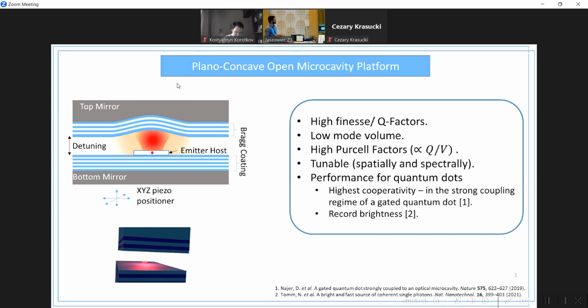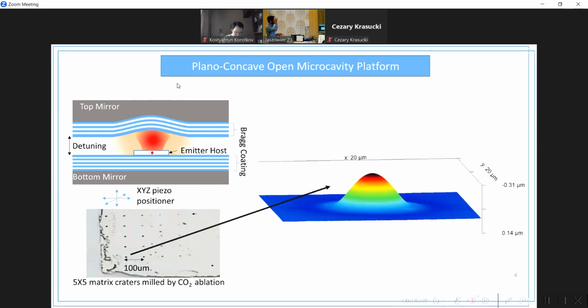Moving on, let's take a look at the sample that we have. This is the top mirror that we are using. These black dots that you see are the craters, and it's worth mentioning that this mirror was produced in Basel by the CO2 ablation method. On top of that, they deposited the dielectric structure, and this is the AFM image of the top mirror.